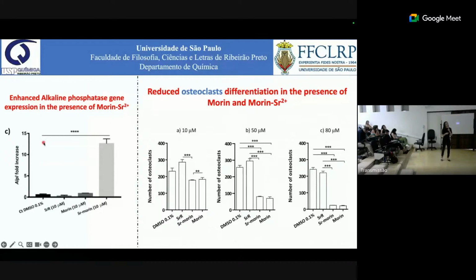But we also investigated the effect of morin and strontium morin on the differentiation of osteoclasts. And we see here that compared to strontium ranelate, using the new compounds, we completely reduce the differentiation of osteoclasts using low concentrations. So if the problem was the concentration of strontium ranelate that was dangerous, we found a good substitute for this drug that can control the differentiation of osteoclasts, at the same time enhancing the activity of osteoblasts.